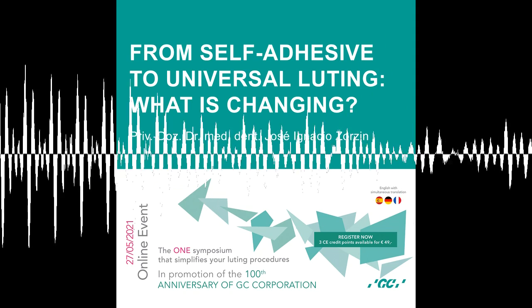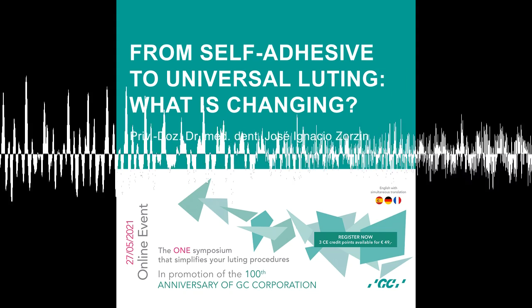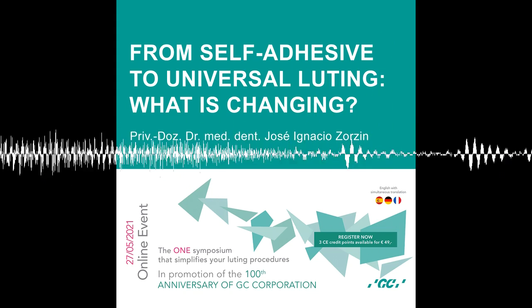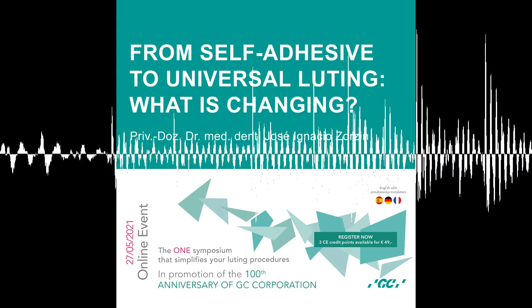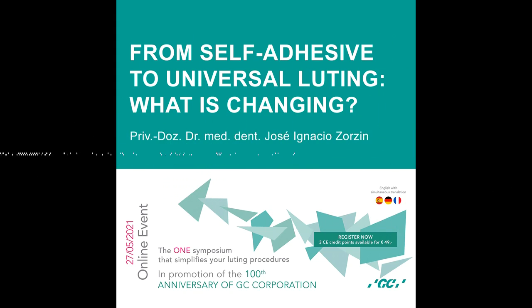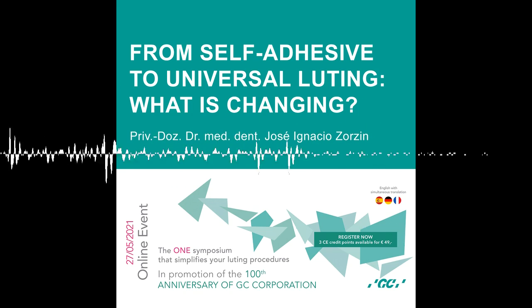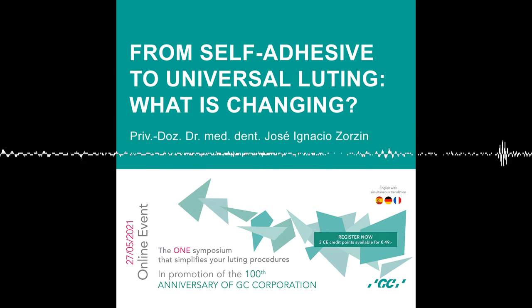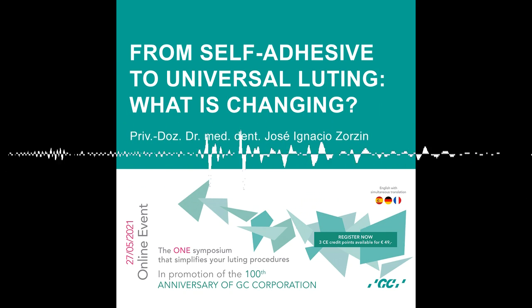What would be the other way around? Just to remove it with a brush? Remove it carefully with a brush, and then, for example, put an air block on the side, like glycerin gel, to inhibit the oxygen layer. However, this would be more like the protocol for a conventional adhesive luting with a composite.